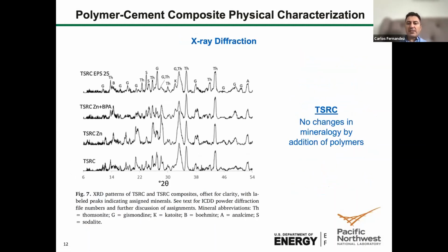Nevertheless, for thermal shock resistant cement, which is a cement based on aluminates and silicates, not only silicate hydrates but also aluminates of calcium, we don't see any changes in the crystal structure for any of the 3 polymer formulations. I don't understand exactly why, but in this case, this formulation may need a retarder because after 24 hours, they form the final or close to final products of hydrated cement.